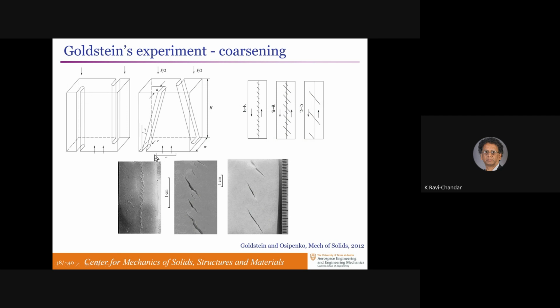When you allow them to grow by a factor of 10, I think, in length, you see that the number of daughter cracks is smaller and the distance is greater. So these cracks that started, they don't make it all the way through as you progress. They shield some of them and only a few of them grow. You make them grow further out from the parent crack, even fewer of them survive, and they become bigger. So there's a coarsening and a corresponding increase in the spacing between the daughter cracks.